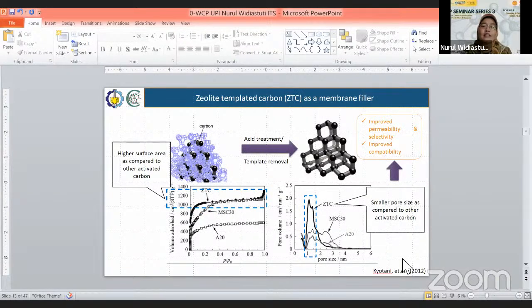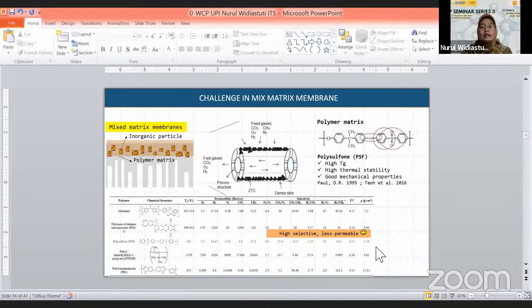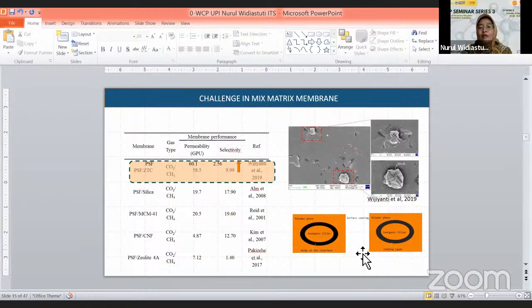Here are the advantages of using zeolite templated carbon to improve the permeability and selectivity, and also the compatibility, because the material has a higher surface area compared to other activated carbon, and also a smaller pore size compared to other activated carbon. And the challenge in mixed matrix membranes when preparing the materials is that, in general, they have a specific problem called voids that are produced at the interface of the inorganic filler with the polymeric matrix. The voids can reduce the selectivity and in general reduce the performance of the membranes.